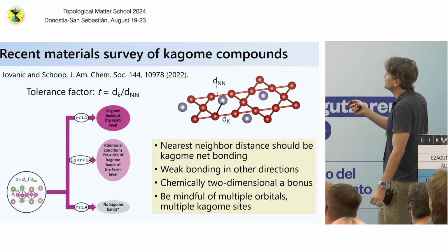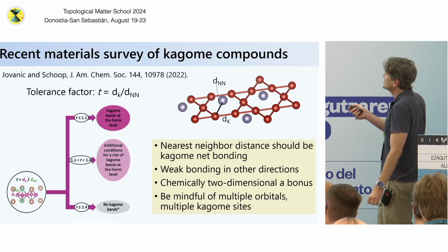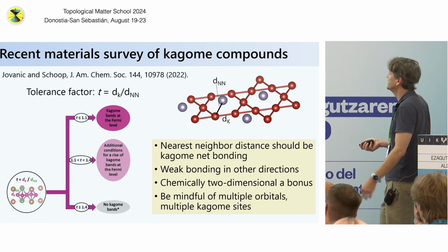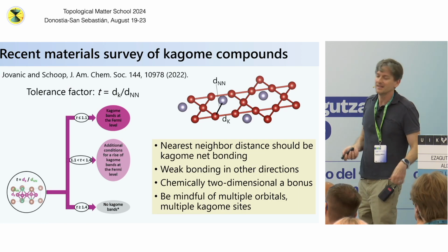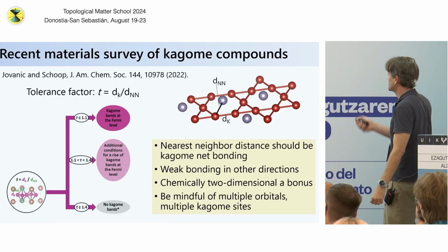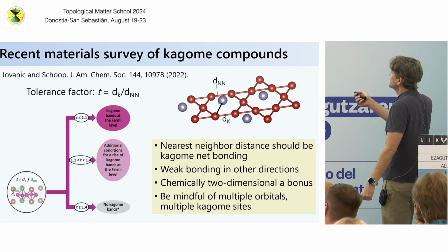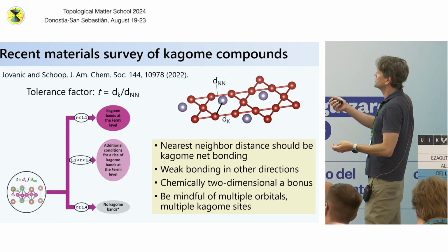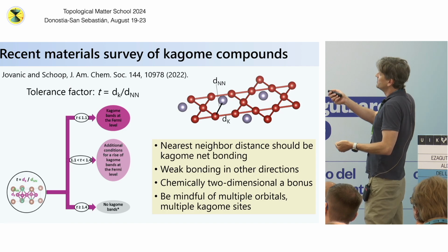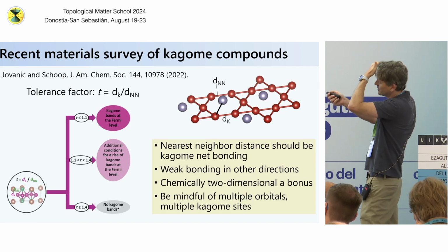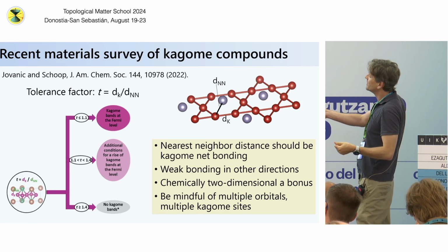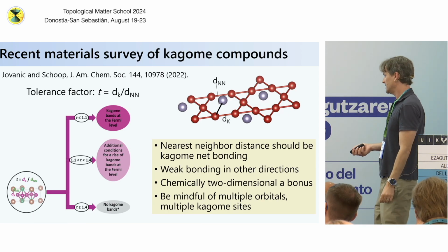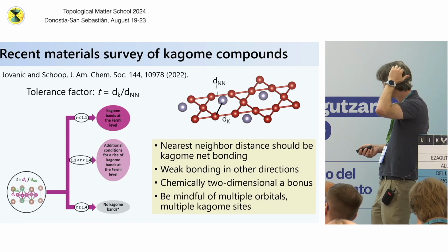When you define a Kagome net, you look at the distance within the net relative to bonding with other atoms outside of the net to understand how Kagome this material is. So you find a Kagome network, but then how isolated will it be in the lattice and how much will it contribute to the band structure, from regimes where Kagome bands are expected at the Fermi level to the opposite extreme, a three-dimensional network that doesn't map directly onto anything you would expect from the Kagome network.